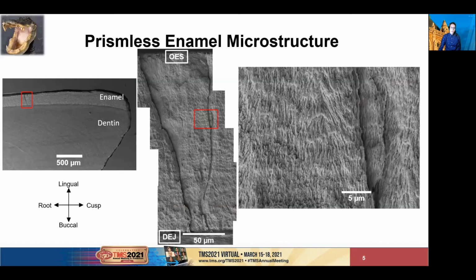On this slide is a buccal lingual section of an American alligator tooth that's been polished and etched, and we're looking at the lingual surface relatively close to the cusp. This tooth was around 15 millimeters tall total, so we're only seeing the cuspal region right here. In prismless enamel, the microstructure consists of repeating arrangements of hydroxyapatite nanocrystals that run primarily normal to the dentin enamel junction in a straight line to the outer enamel surface. Also notice that there are no distinct prisms here, just nanocrystals. You can, however, see some growth lines where there is a slight overlap between crystals. However, not all regions of the enamel are so linear.